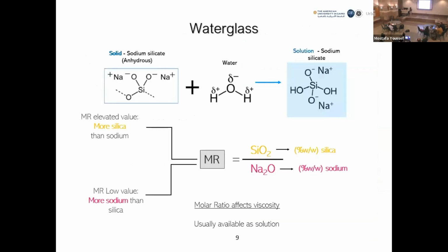For this reason, I started to investigate water glass, or sodium silicate. As reported here, you can find the molecular structure of a sodium silicate in solution. As the name says, sodium silicate is composed of two main parts, SiO2 and Na2O. The ratio between these two components is very important because it affects several parameters of sodium silicate, in particular viscosity. And as I told you, if I want something that is injectable into the masonry, it is a very important parameter that I need to keep in mind.